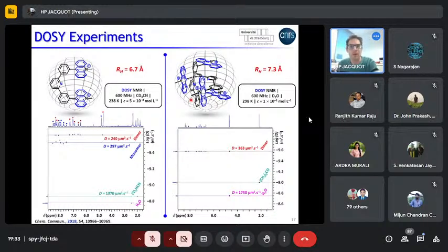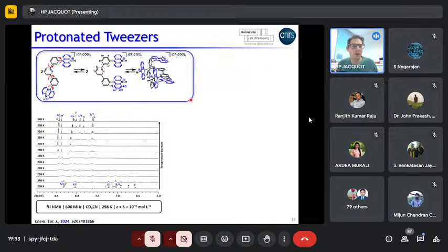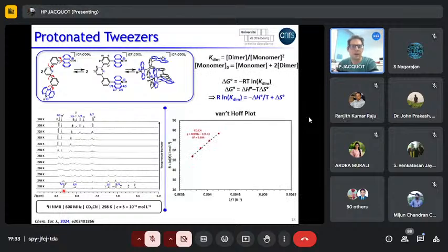So of course I wanted to play with this family of molecules, and we looked at the influence of protonation. So we changed the N-methyl acridinium by the NH acridinium, so protonated acridine. So it has roughly the same behavior in acetonitrile as the methylated compound. So at different temperatures, we can estimate a binding constant because we have a different ratio between the monomer and the dimer. And like this, we can go for a van 't Hoff plot analysis that allows the determination of the enthalpic and entropic contribution of the molecule in this solvent.